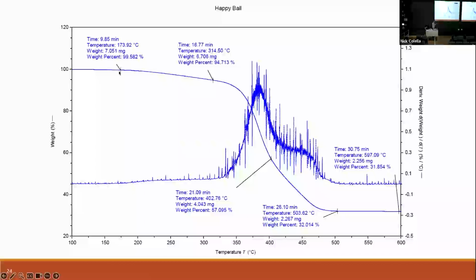We don't have any solvents in there. We're just getting a little bit of degradation of the polymer first, and we see a big spike. The first blue curve, that is the degradation curve, kind of slopes down all the way, leaves about 30% residual mass. The second curve on here is just the derivative of the first curve, which helps us see the rate of mass loss, which can be helpful for analyzing the data more closely.